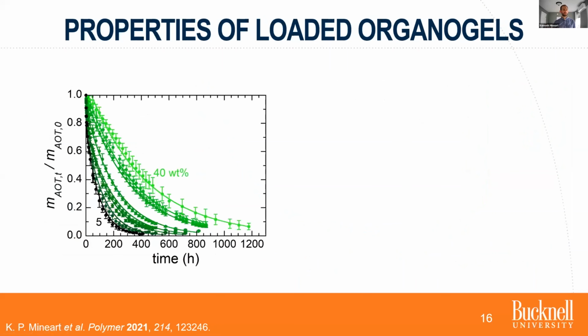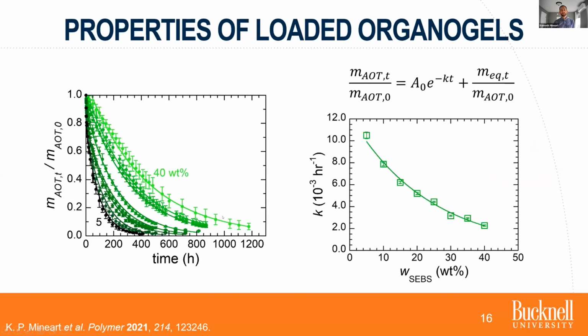So we can do this for all of these different gels that I showed you structural information for, from 5 to 40 weight percent triblock copolymer. These all initially have 1 weight percent AOT. And as you might expect, the more copolymer concentration there is, the slower the release of AOT from these gels. We can kind of quantify that, and there's some complication, which I'll come back to in a second.